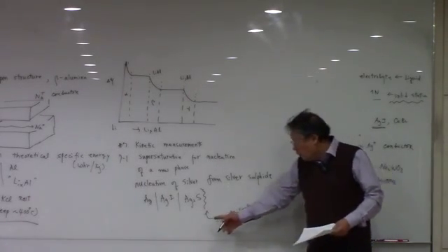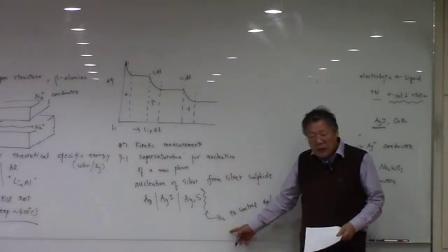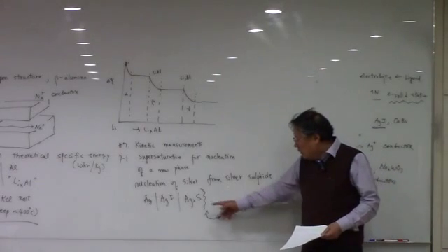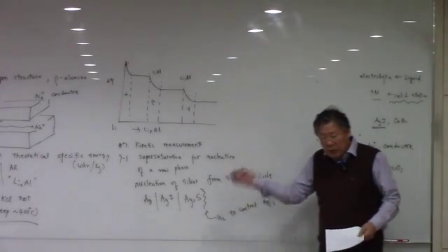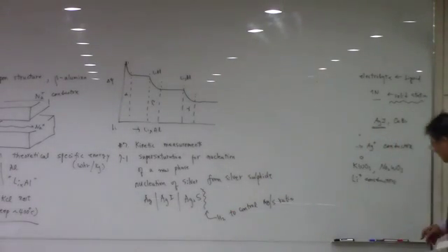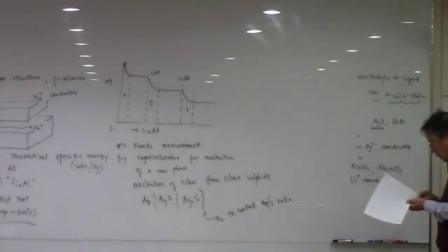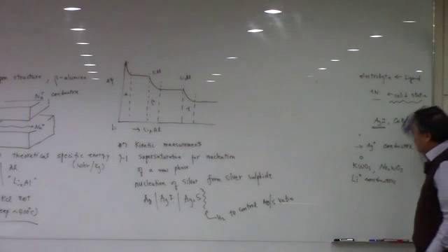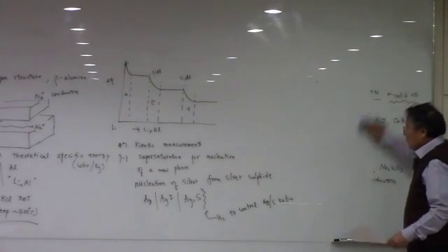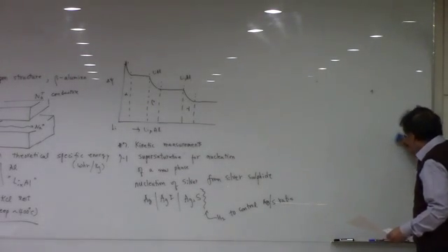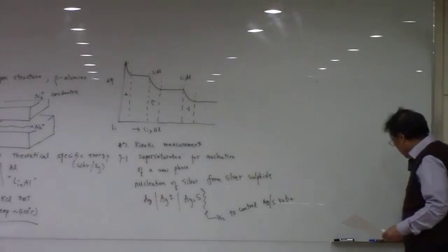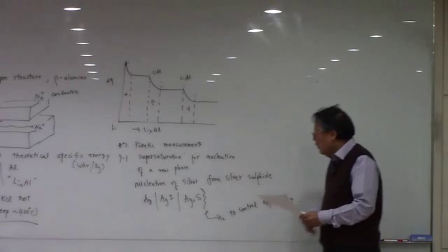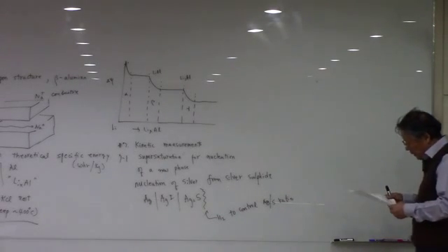Okay, if you blow the H2 at elevated temperature to the Ag2S, then the S is going to be reduced so that we can increase the Ag to S ratio. And then with the different ratios, we have a different potential between these two, so that we can measure.